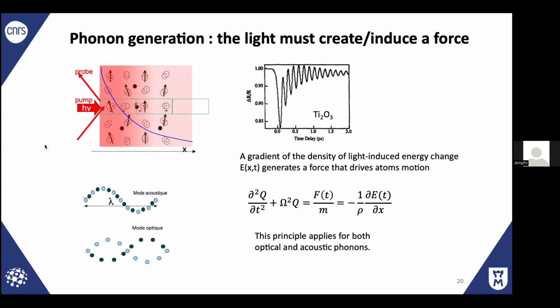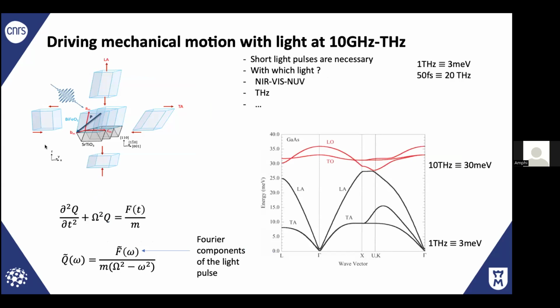Here in the green, these are the unit cells of atoms. If you want to generate an optical phonon, you have to modify the distribution of energy in the unit cell. If you want to generate an acoustic phonon, you have to induce gradients, meaning you have to modify the coupling between the different unit cells, which is exactly the essence of the symmetry of motion of an acoustic wave, an acoustic phonon. So if you take into account this oscillator equation, of course, if you want to generate phonons in the Fourier domain, you need to have such a Fourier component in your force. And this is possible only if there is a spectral wave which works at that frequency. Of course, if you take a typical 50 femtosecond laser pulse duration, you can spread nearly over the entire frequency range here. So typically, this is the case of gallium arsenide here. So 10 THz is roughly 30 meV.